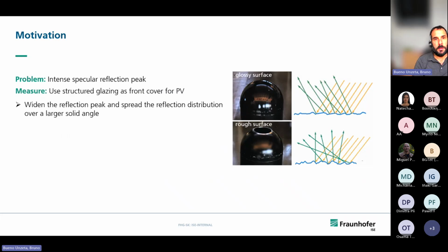So the problem is clear. We have an intense specular reflection peak from the glass surface, and the measure to mitigate the problem is to use a structured glazing as front cover for BIPV. With a structured glazing, we widen the reflection peak. We spread the reflection distribution over a larger solid angle, and therefore the overall intensity is lower.